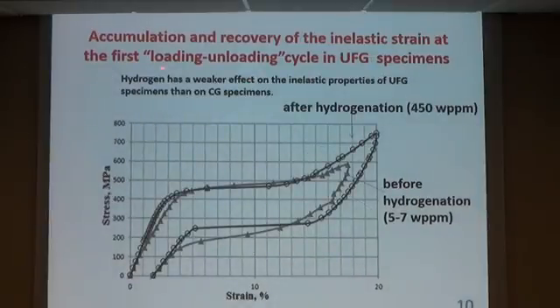It is accumulation and recovery of inelastic strain at the first loading-unloading cycle in ultrafine grain specimens. Hydrogen has a weaker effect on the inelastic properties of ultrafine grain specimens than coarse grain specimens.